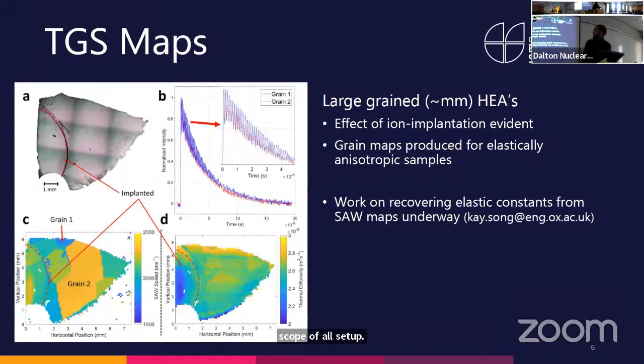This is a large grained high entropy alloy, which is elastically anisotropic. So in this surface acoustic wave speed map, you see different elastic properties, or different wave speeds, in different grains, which gives out our grain map. For the thermal diffusivity, there isn't a big difference from grain to grain, but we see the region that was implanted with, I think, vanadium ions in this case for this sample.